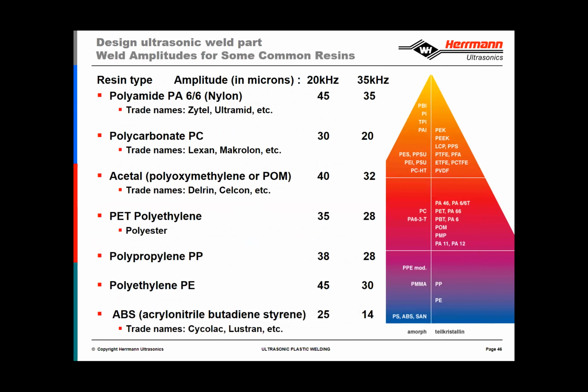Here are some amplitude requirements for specific materials. These half dozen or so materials are the most common, the most typical that we see. And you can see that things like nylon, which is a semi-crystalline material, has a higher amplitude requirement than, for example, ABS down at the bottom of the chart, which has a much lower amplitude requirement. So depending on the material that you choose, again, primarily we adjust the amplitude depending on the material.